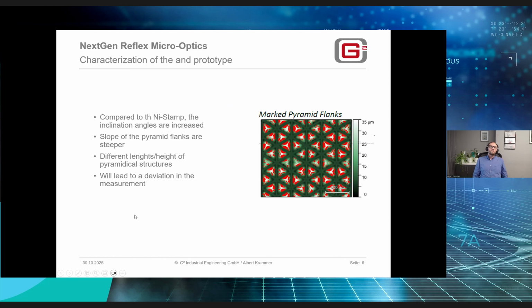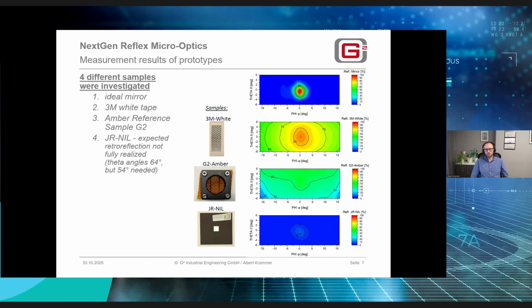What we observed together with Joanneum, or what Joanneum observed in that case, is that the inclination angles, you remember that the angles of these pyramids are the most critical factor to get the total reflection, changed a little bit during the production process. So that means that the slope of the flanks is steeper. Yeah, there were different lengths and heights compared to the simulation. And of course, you will see in the measurement results that this will lead to a slight deviation. But at least we know the reason for that, and I will explain a little bit later what the defect was.